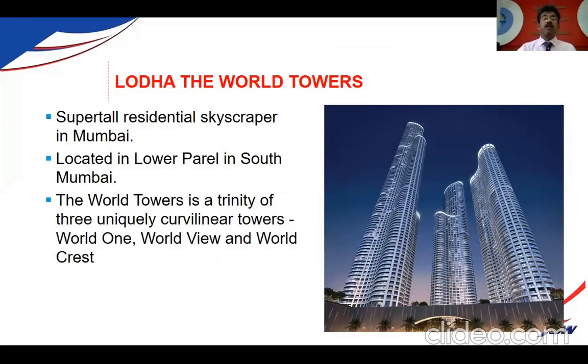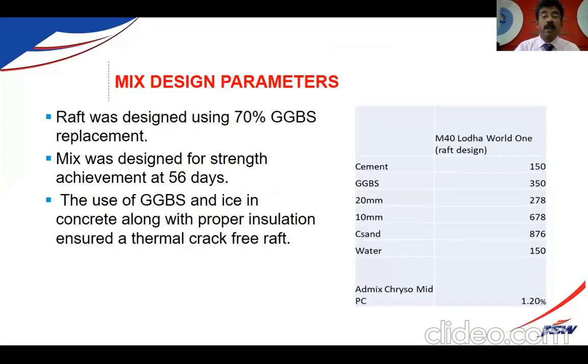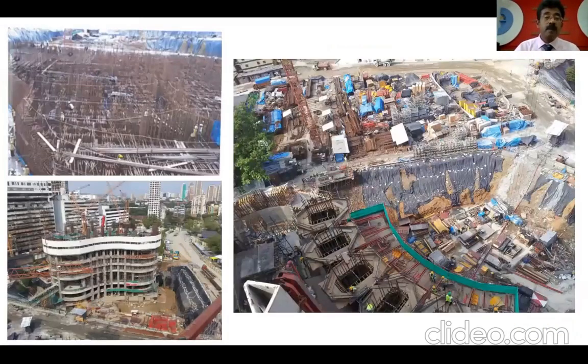Lodha, one of the tallest skyscrapers built in India, has used this product at a higher replacement. GGBS, they have used 350 kg, cement 150 kg, for an M40 grade raft. Especially this higher replacement of GGBS was done to bring down the temperature because the raft was about 5 meters thick. 70% GGBS they have used to reduce the thermal cracking. You can see the pictures, how it is done.